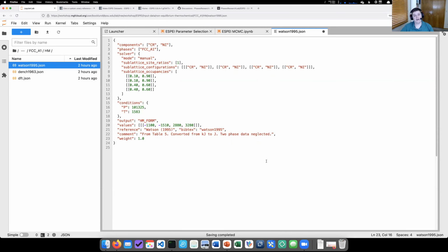And so if you have a weight of 1, that's the default, so this would basically be a no op here. Weights greater than 1 make that data more important. And what you're doing in effect by adjusting the weight is adjusting the inverse of the standard deviation of this data. We define the likelihood function for every piece of data as a normal distribution. So we assume the residuals are normally distributed, centered at 0 with some standard deviation that depends on the data type. And so we provide some default standard deviations.